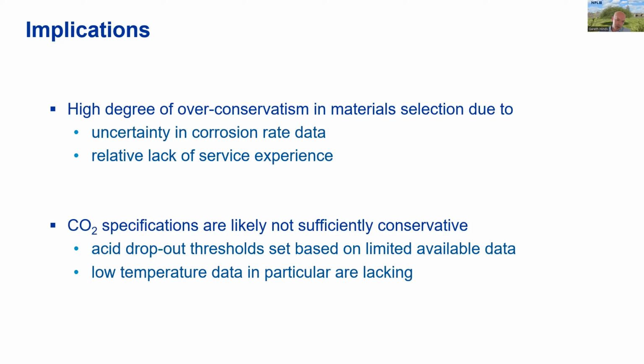The second thing, and Monica's already touched on this, is that CO2 specifications are tightening all the time. They're likely not sufficiently conservative, particularly because of acid dropout. This is where the different SOx and NOx and H2S impurities in particular can react together and combine with the water to form very acidic aqueous phases, essentially nitric and sulfuric acid that will eat through the pipeline material. And thresholds for acid dropout are still based on very limited available data, and particularly data at low temperature. So we need to gather more information and more understanding on acid dropout in particular to be able to set more reliable and cost-effective CO2 specifications.